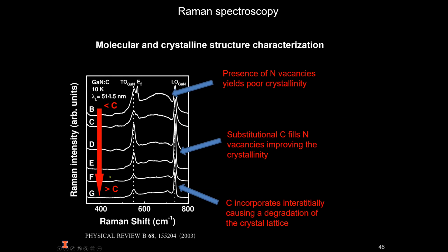For low incorporation, the crystallinity of the sample initially improves, because the carbon starts to fill the nitrogen vacancies present in the as-grown material. With increased incorporation of carbon, the crystallinity degrades again, because carbon then starts to incorporate interstitially.